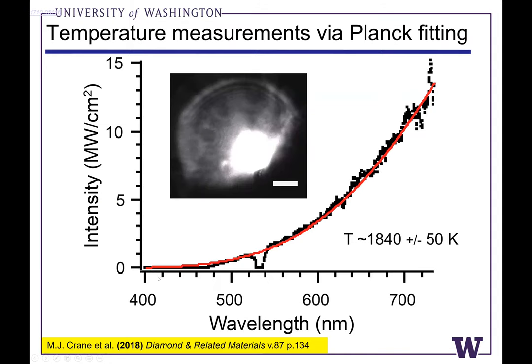Is this realistic? And we started to look more at what the temperatures were during the experiment. We could easily melt argon. It was clear we could melt argon. But typically to extract the temperature, we're using the Planck emission from the laser heated focal volume. This is an image of a laser heated carbon aerogel target sample. If you really crank up the laser power, you can illuminate the entire room from a spot size that's just 100 microns across. We collect this sort of visible luminescence, this Planck luminescence, black body radiation from the laser heated sample. And we fit this with nonlinear least squares fitting to approximate the temperature on the order of 1800 or 1900 Kelvin.